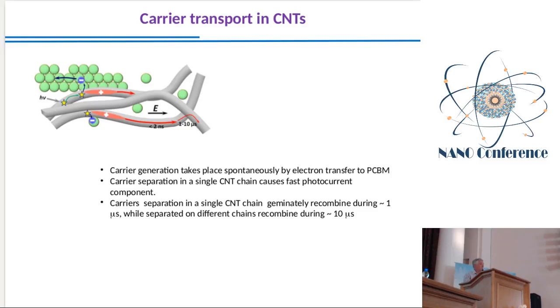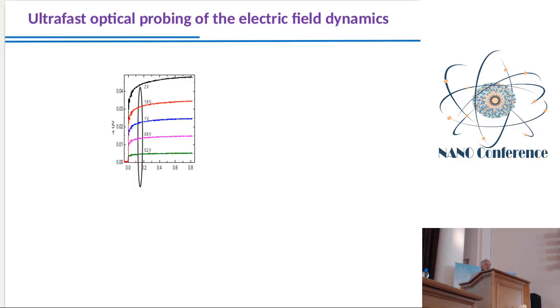Now, we decided to investigate this very fast initial photocurrent part, which we could not investigate by using our photocurrent investigation technique. So we used a more complicated technique. It's a little bit tricky. We investigated, in fact, the electric field inside our material, directly inside our material, by using a femtosecond technique.